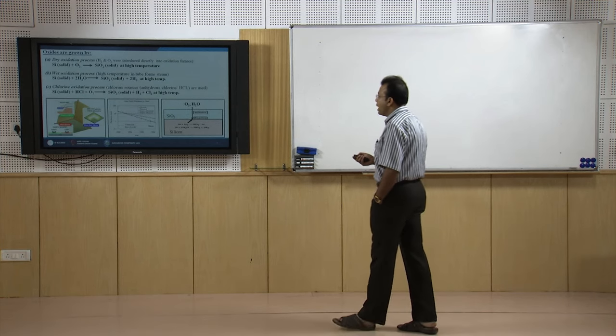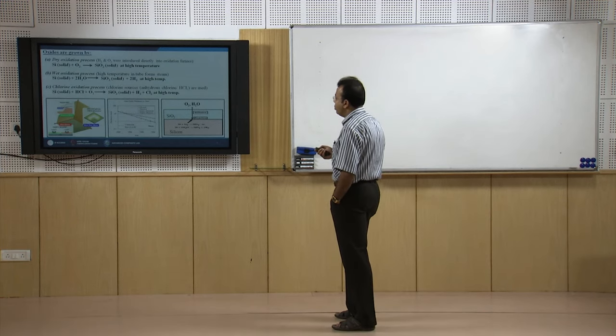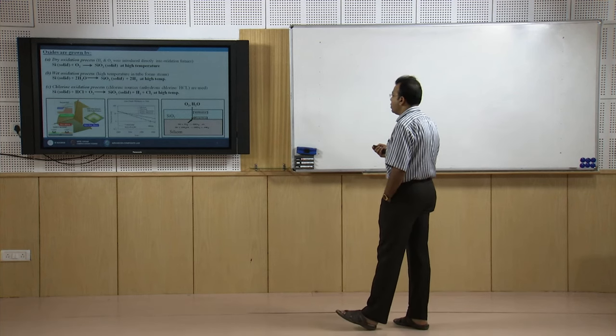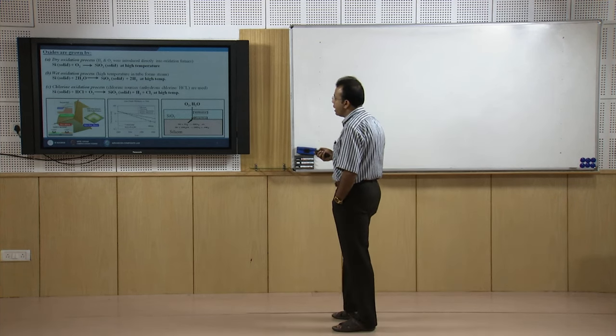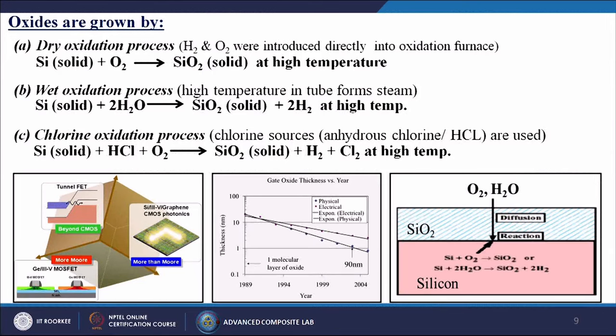The first one is called the dry oxidation process, where oxygen is introduced directly into the oxidation furnace. The reaction looks like this: silicon in solid form plus oxygen forms silicon dioxide at high temperature. Wet oxidation process. Here in the dry one we use oxygen as a gas, but when we talk about the wet oxidation process, we use water vapor. So high temperature in the tube forms steam. So what is the reaction? Silicon solid plus 2 water forms silicon dioxide solid and 2 hydrogen gas at high temperature.